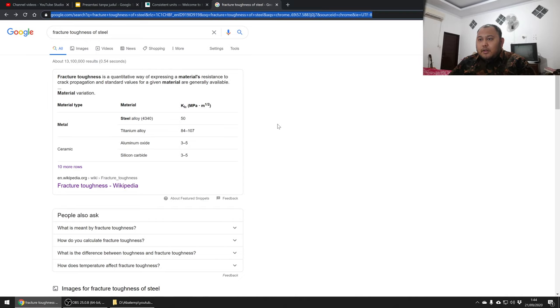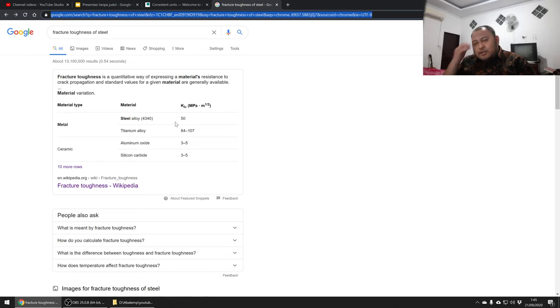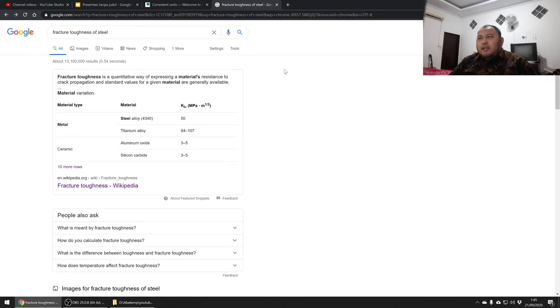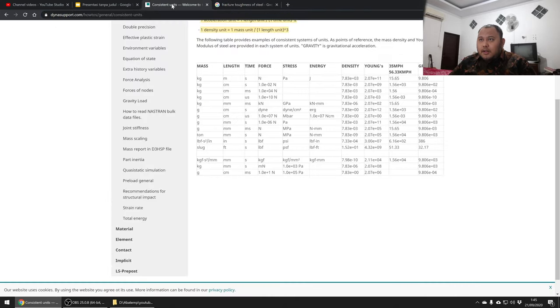We are going to calculate the stress intensity factor - not fracture toughness, because fracture toughness is the material property - and then compare with the critical stress intensity factor from experimental data. Imagine you have a specimen and before doing the test using a tensile test machine, you want to check how much load is required to extend the crack. We will model this metal with K1c = 50 MPa√m, meaning under mode 1 the crack will extend when the stress intensity factor reaches 50 MPa√m.